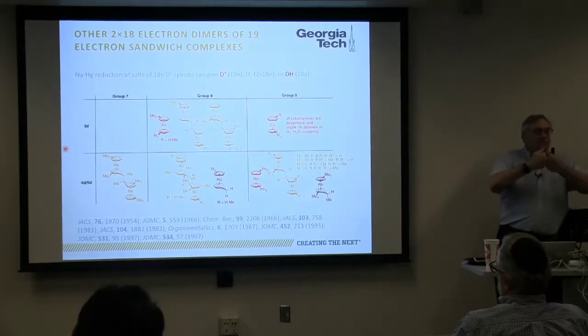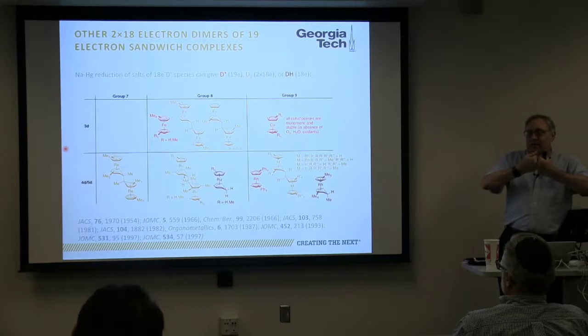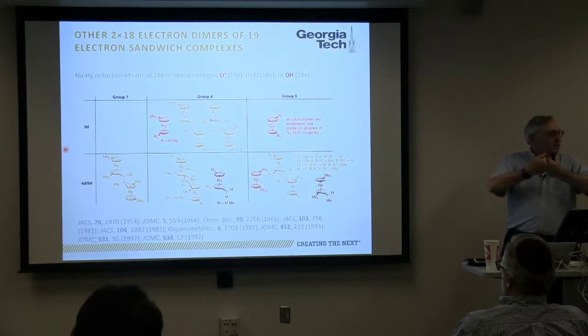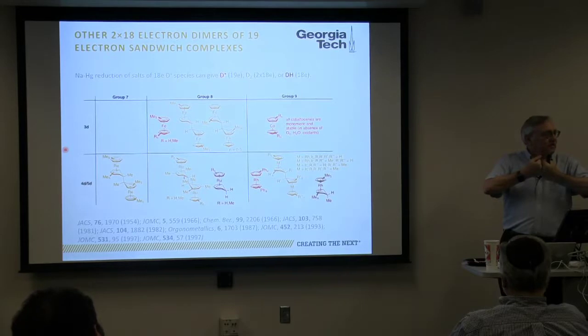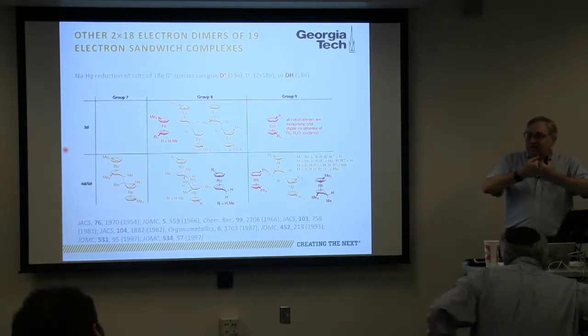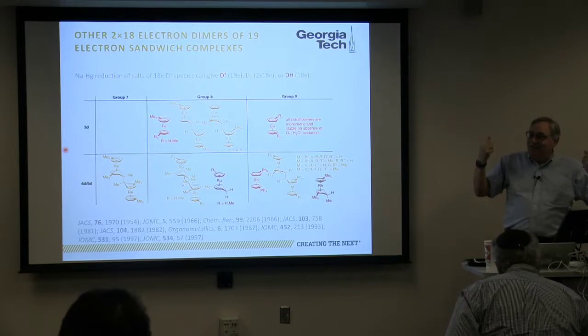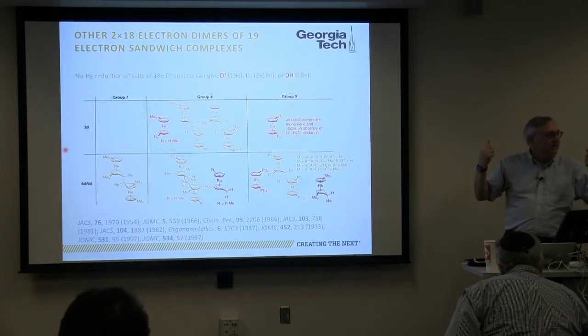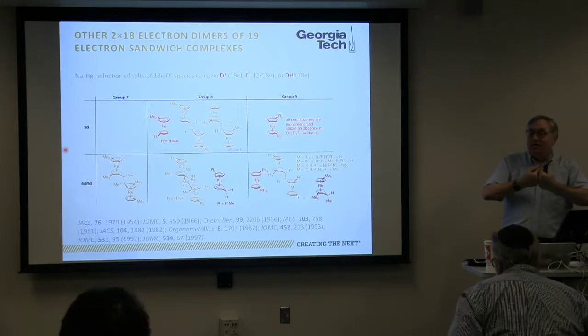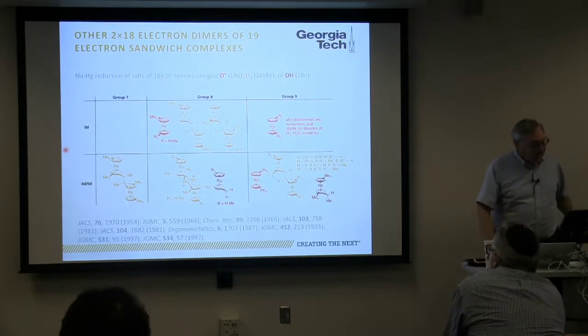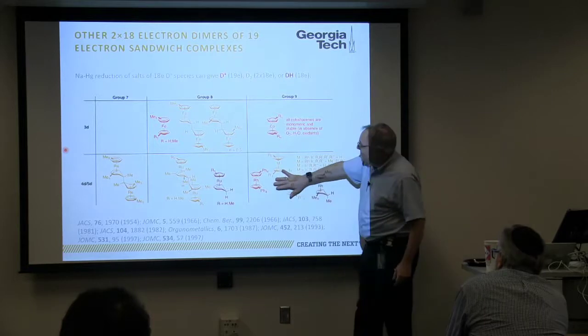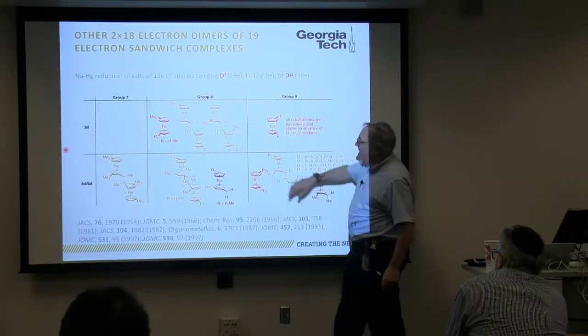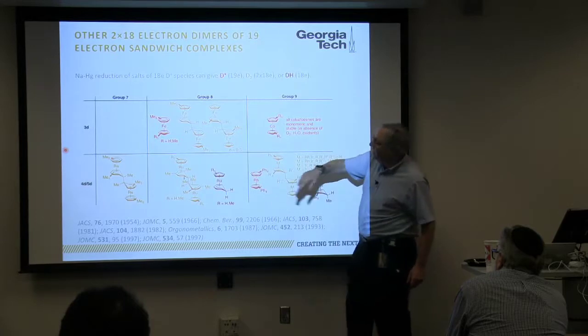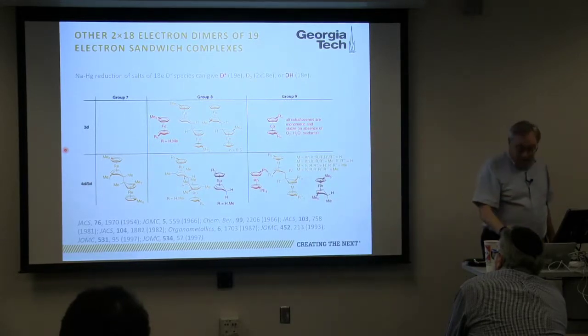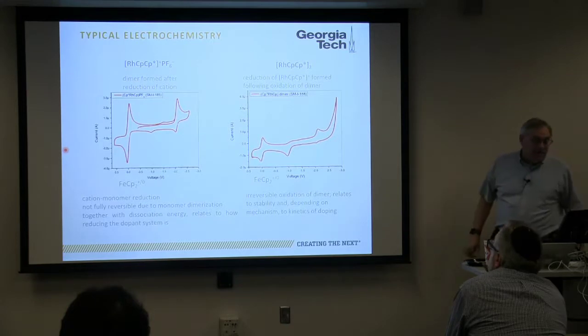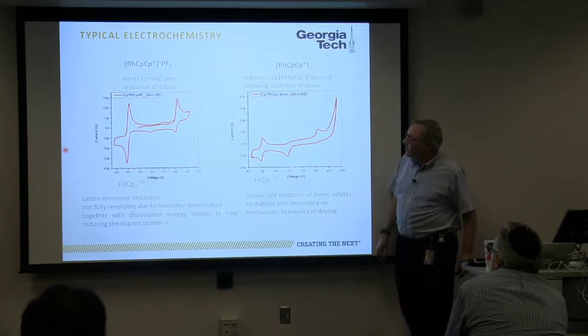And what was also known is that you could heat this material, okay, the dimer of this material, and on a cold finger at 77 degrees Kelvin, you can basically isolate the 19 electron compound, which is highly reducing, but if you warm it up, it will dimerize again. Okay? So there are a series of these things, some based on the elements of rhodium and iridium, some based on iron and ruthenium, and there are even some that are based on osmium. Okay? And then we discovered something actually by reading the literature on some of these compounds.